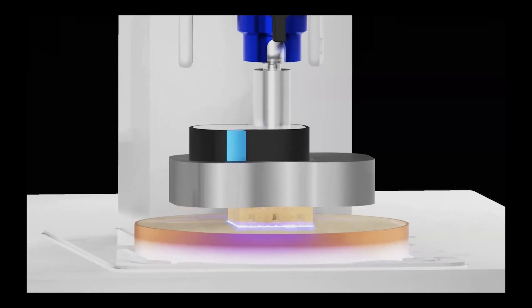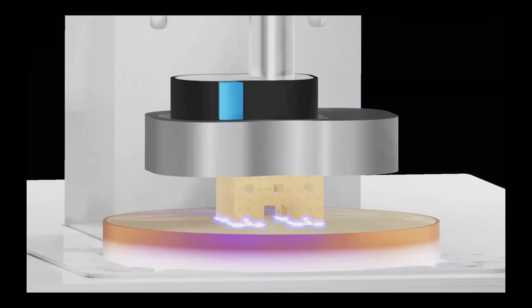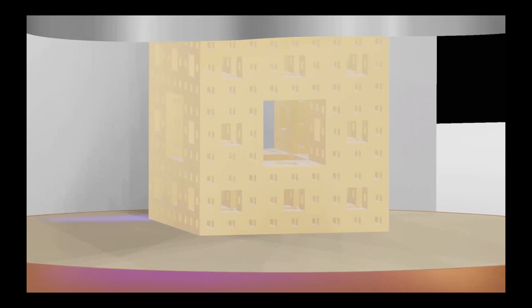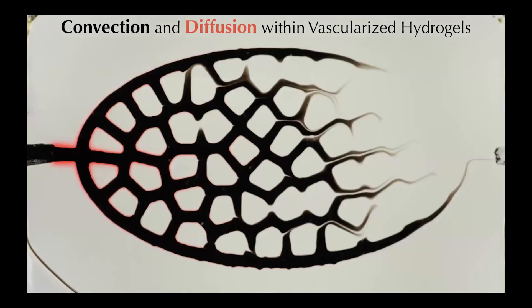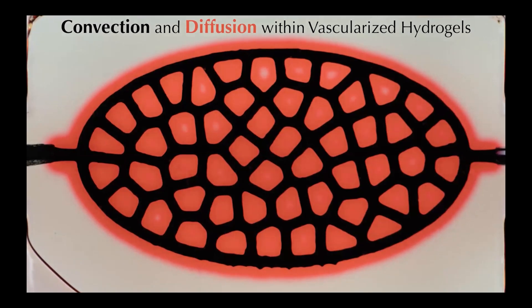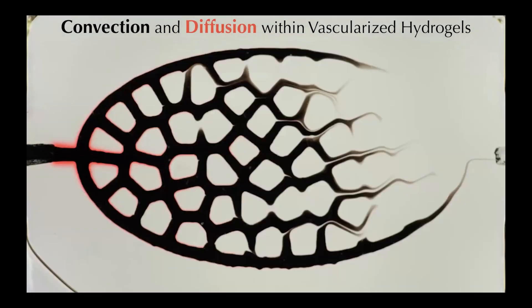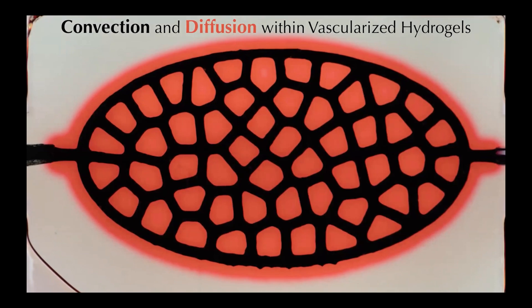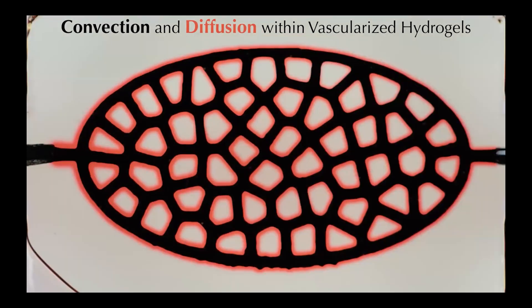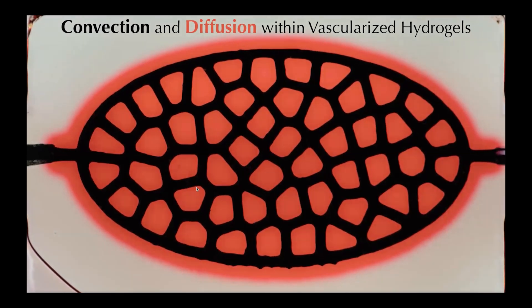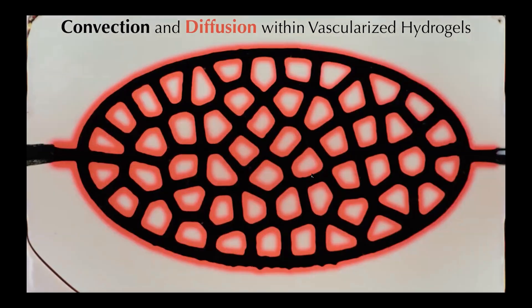We're using a layer-by-layer projection where a light-sensitive polyethylene glycol diacrylate gel is being polymerized. We can also do this with gelatin methacrylate in degradable settings. Every individual layer is a different image getting projected, effectively building up the object. What we like about using 3D printed hydrogels is you can make really intricate blood vessel networks. Here we're perfusing two different materials: colloidal black India ink going in, which gets trapped inside the vessels.